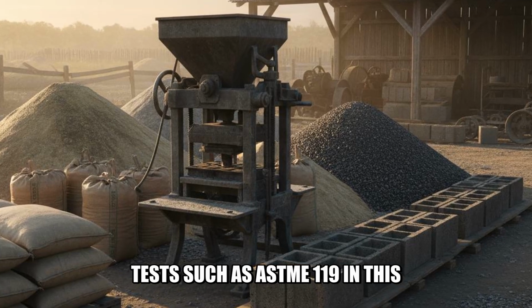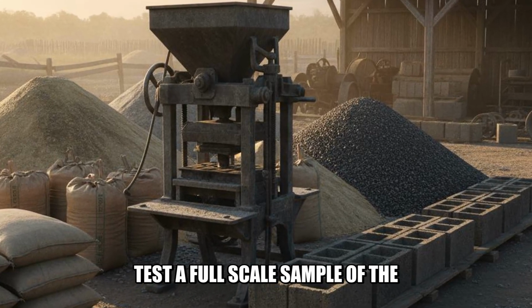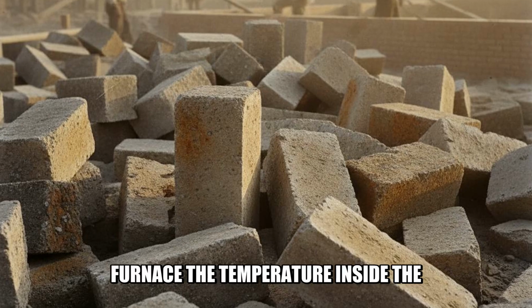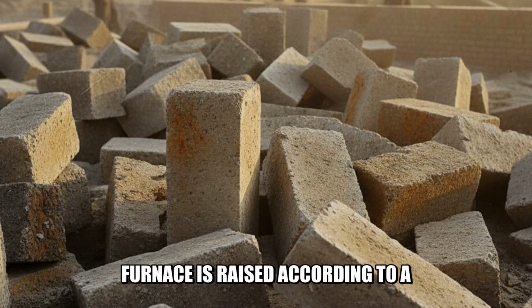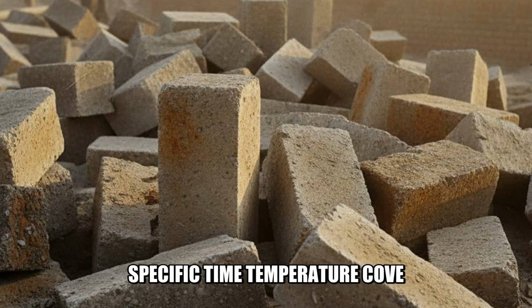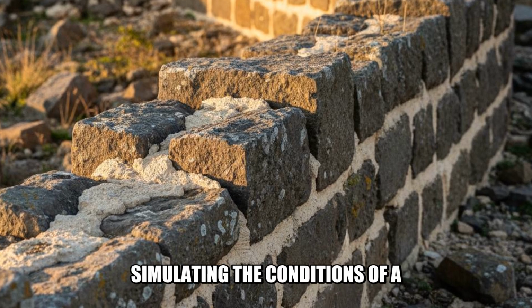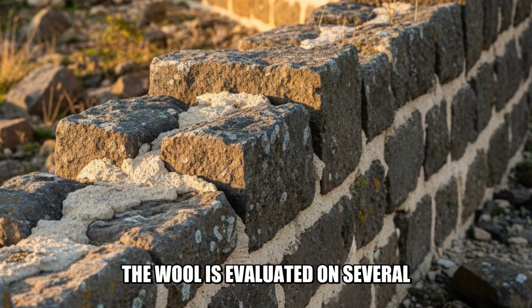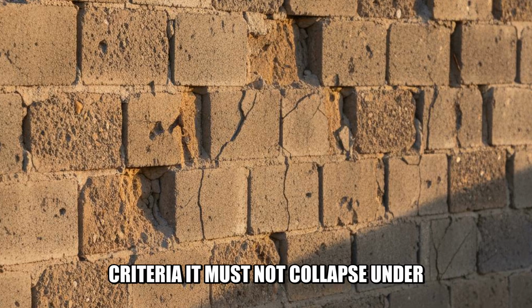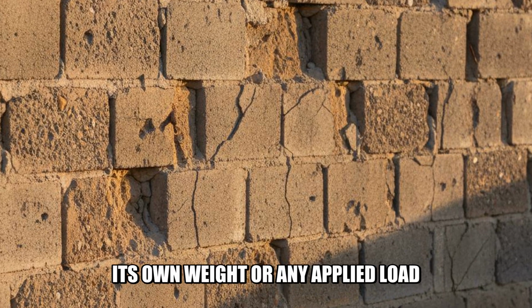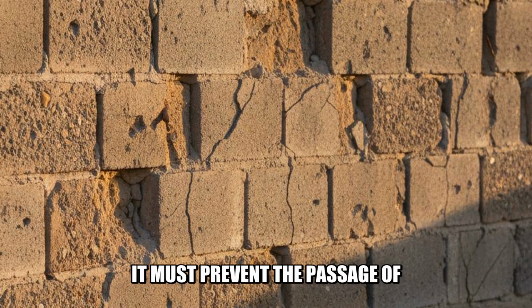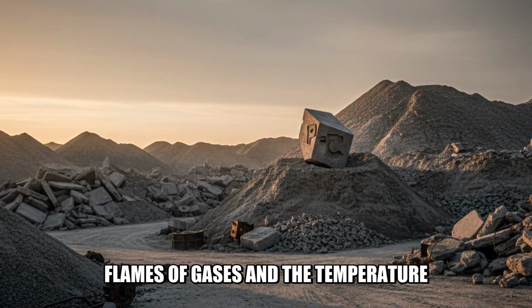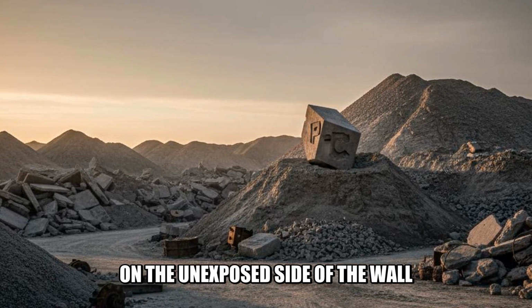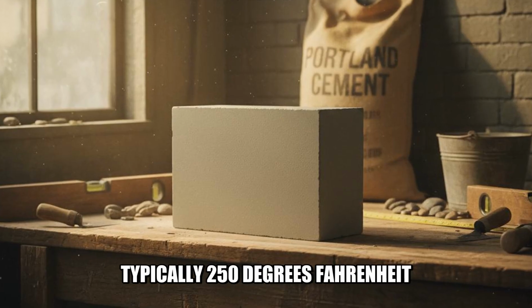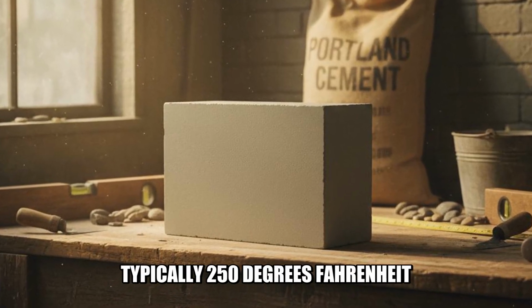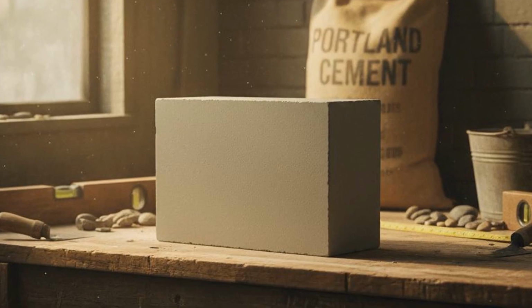ASTM E119. In this test, a full-scale sample of the wall is built and placed in a large furnace. The temperature inside the furnace is raised according to a specific time temperature curve, simulating the conditions of a building fire. The wall is evaluated on several criteria. It must not collapse under its own weight or any applied load. It must prevent the passage of flames or hot gases. And the temperature on the unexposed side of the wall must not rise above a certain limit, typically 250 degrees Fahrenheit, above the ambient temperature.